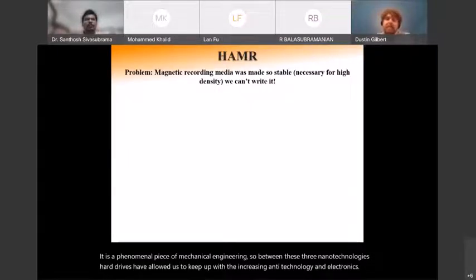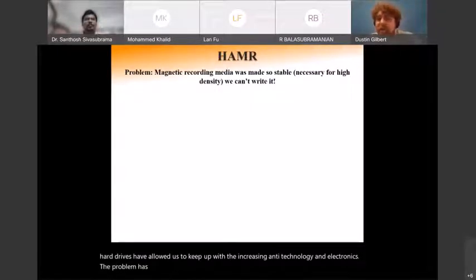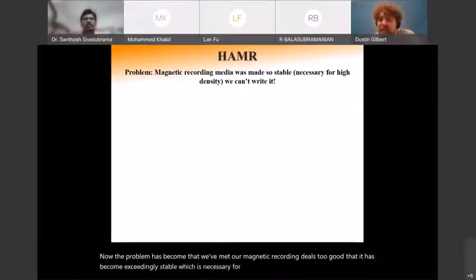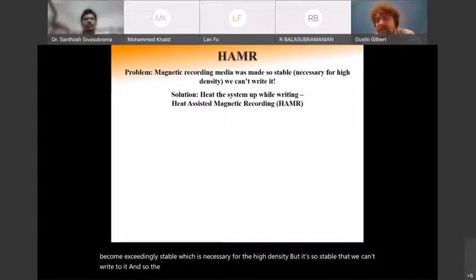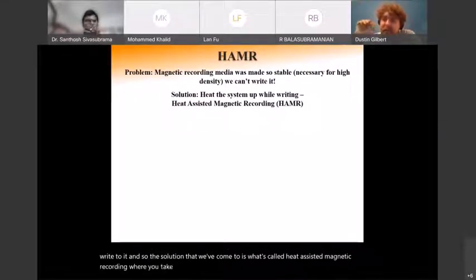Now the problem has become that we've made our magnetic recording materials too good. It has become exceedingly stable, which is necessary for the high density, but it's so stable that we can't write to it. And so the solution that we've come to is what's called heat-assisted magnetic recording, where you take your data plate and you heat it up before you write to it, and then write to it and then let it cool.